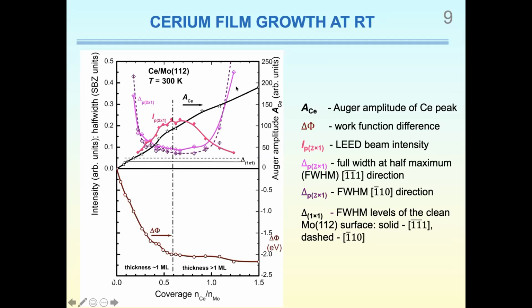It seems that work function difference, Auger amplitude and intensity at first rise linearly with the coverage increasing. Then, with coverage exceeding 0.5, which is the stoichiometric for the primitive 2x1 structure, the work function is stabilized, while Auger amplitude continues growing and intensity of LEED patterns decreases. Taking into account that coverage 0.5 is the stoichiometric, as I said previously, the described changes of overlayer properties can be interpreted as evidence of the formation of a first ordered cerium monolayer, over which a disordered second layer grows.